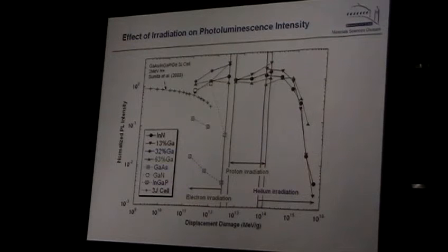So we did this and this shows how it looks. You can damage with different particles, electron, proton, or helium, and scale the damage on the same scale. So this is displacement damage in electron volts per gram. This is a unit of damage. But basically it shows that if you take, let's say, gallium arsenide, gallium nitride, especially gallium arsenide, which is used in current cells, you see that it goes very quickly. The photoluminescence is a measure of quality.